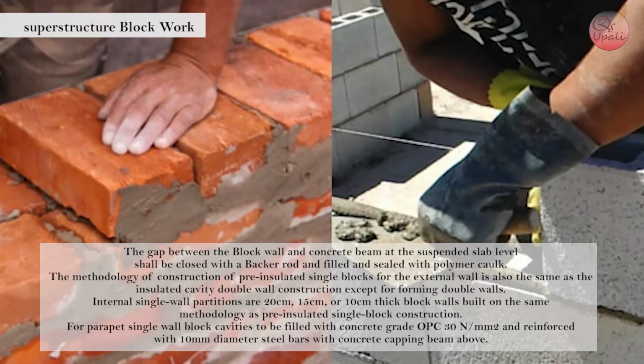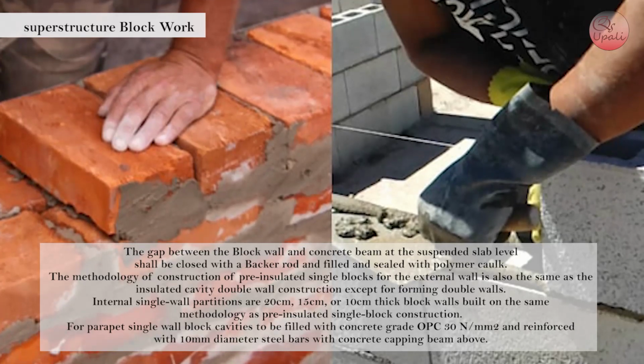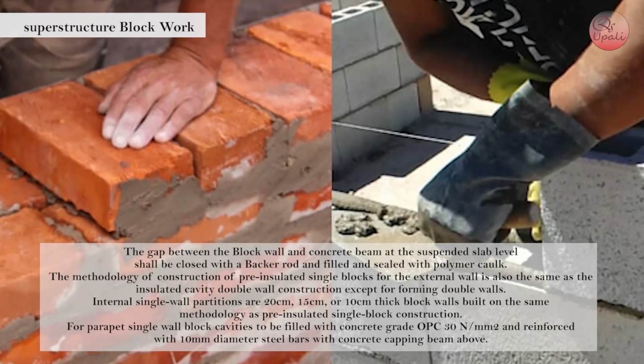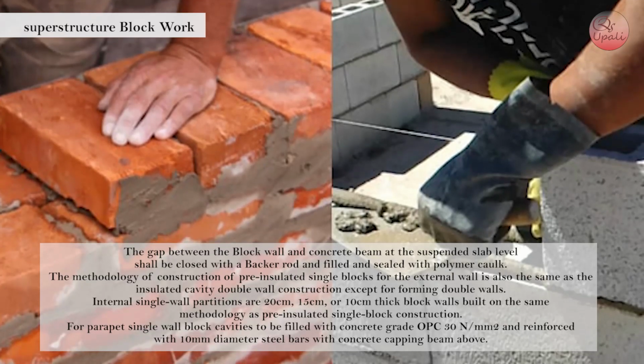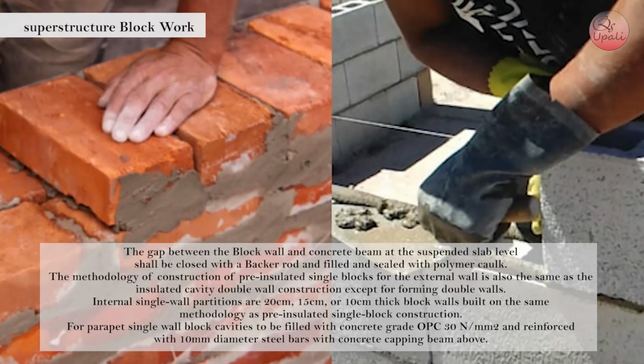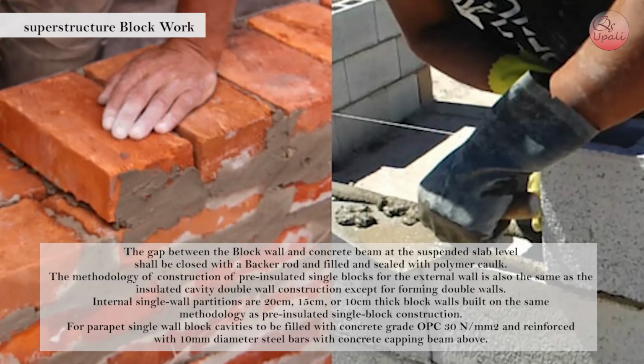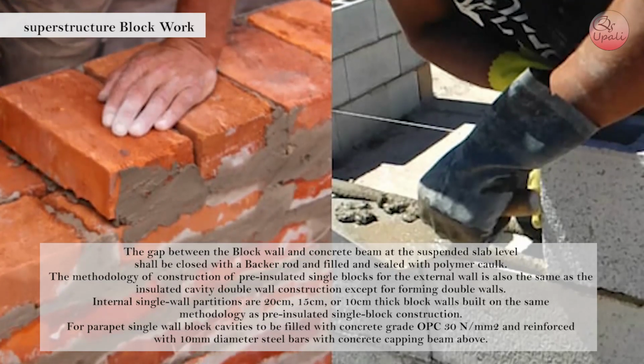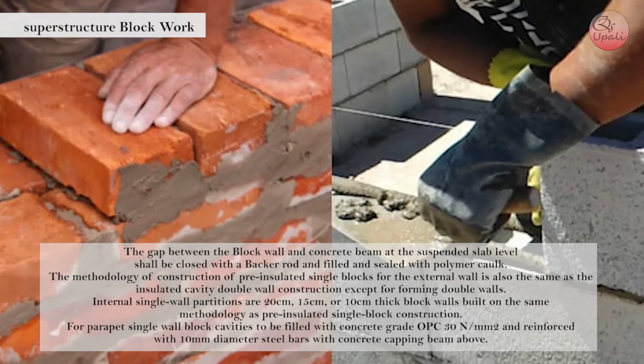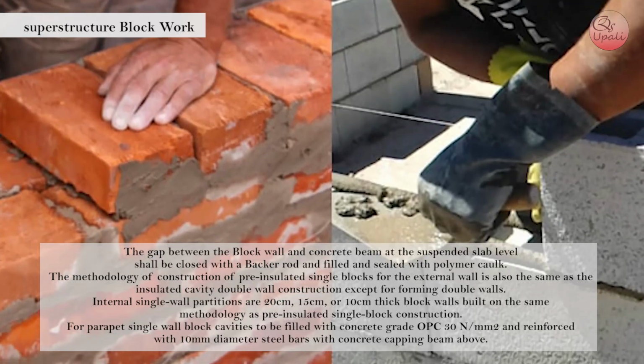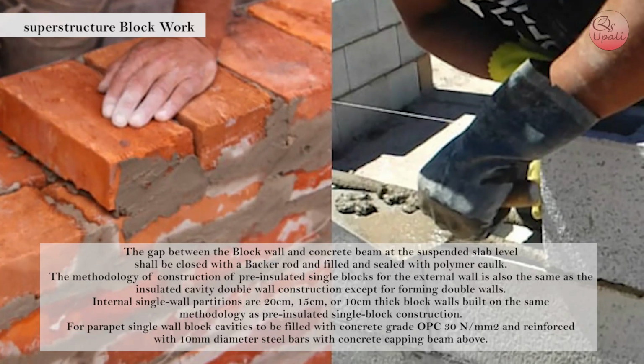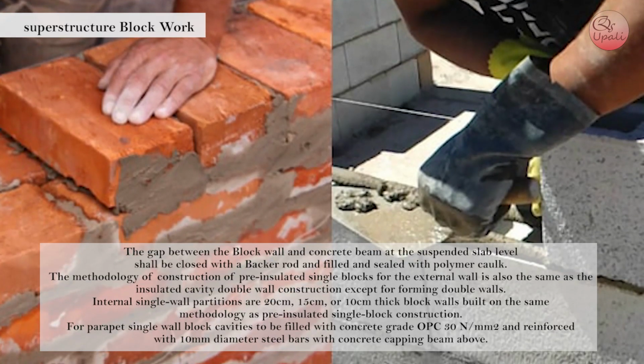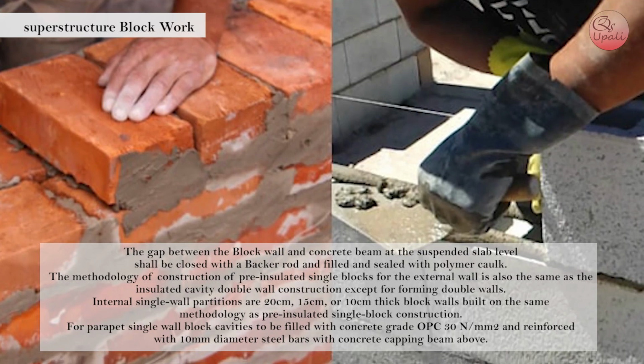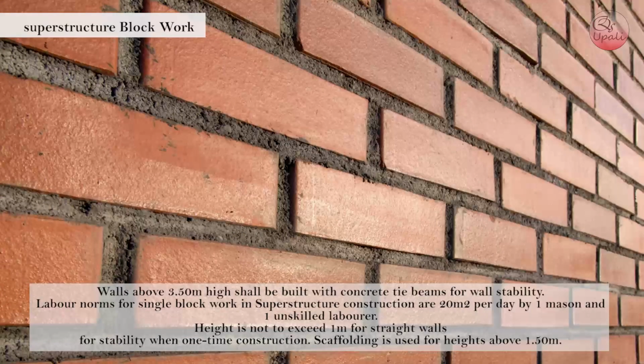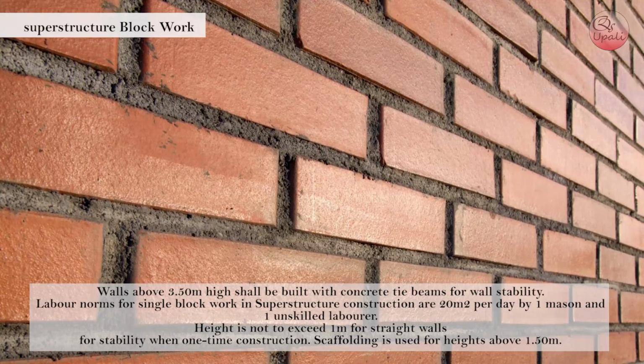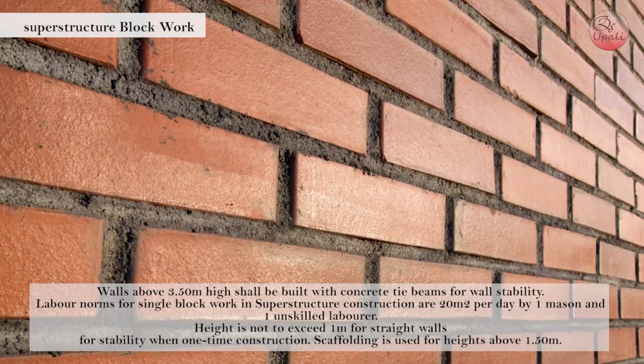Internal single wall partitions are 20 cm, 15 cm or 10 cm thick block walls built on the same methodology as pre-insulated single block construction. For parapet single wall, block cavities are to be filled with concrete grade OPC 30 Newton per millimeter square and reinforced with 10 mm diameter steel bars with a concrete capping beam above. Walls above 3.5 meters high shall be built with a concrete tie beam for wall stability.